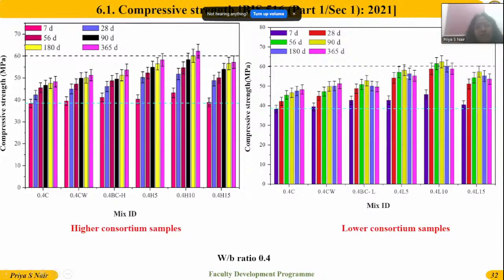up to this yellow figure, right side yellow, this is the lower consortium. So it can be seen that up to 90 days for the lower consortium, the compressive strength was higher. But thereafter a slight decline happened. But it was not below the control one. But in the case of higher consortium, it was moving upward, only in a linear direction, linear growth, linear hike was noticed there.